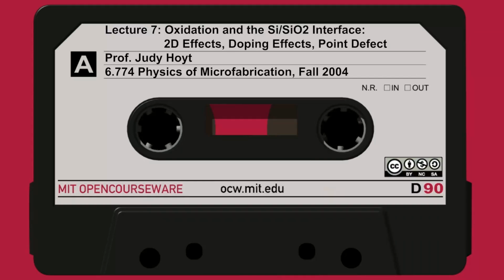Equal amount of boron. So if it were a chemical effect, just the amount of phosphorus atoms, let's say a phosphorus atom chemically causes oxide to grow faster, it wouldn't matter whether you added an equal amount of boron. But if you add an equal amount of boron, you don't change the Fermi level. So this is an argument that says to me that it really is the electrical concentration that's changing. It's the movement of the Fermi level. It doesn't prove it's a vacancy effect, but it gives a little bit more weight.